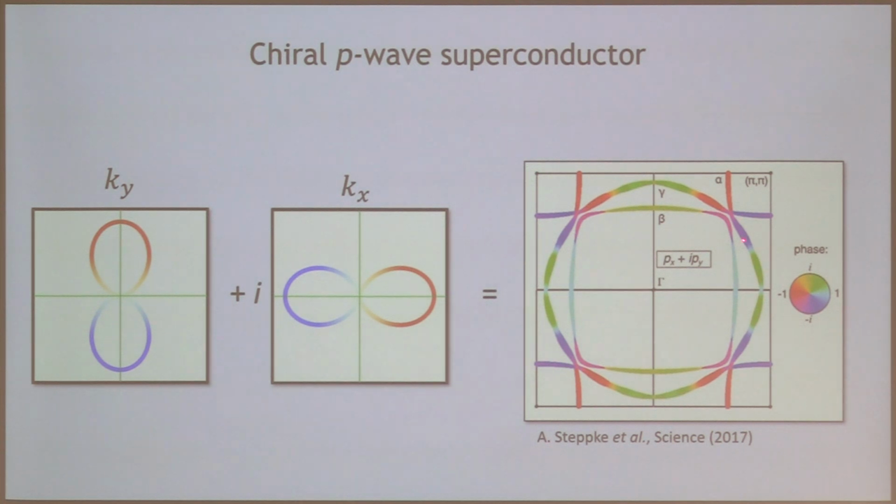This is Clifford Hicks' picture of what the superconducting phase might look like on the strontium ruthenate Fermi surface. It's a beautiful rainbow of phase changing everywhere on the Fermi surface, not just across some diagonals, but it changes continuously. And this is really at the heart of why it might be so disorder sensitive, because if you scatter from anywhere to anywhere, you break a pair because you go to a different phase. Whereas in an S-wave superconductor, the phase is the same everywhere. So lead tin solder is a perfectly good superconductor, just like lead. It doesn't care. That was Anderson.